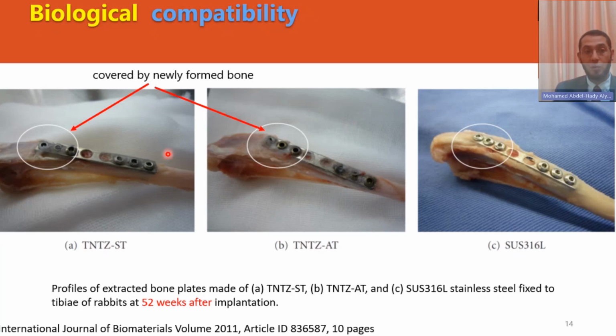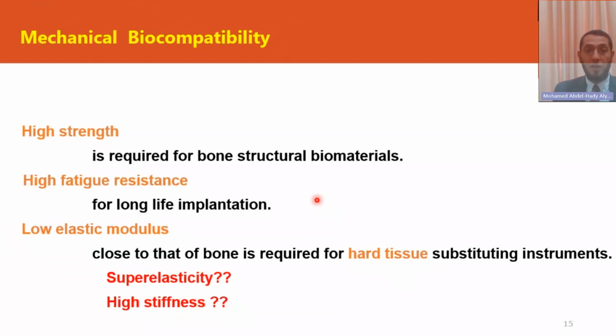Here is an example of the bone plate after implantation. One alloy that's called TNTZ, titanium, niobium, tantalum, zirconium, is good. All elements are very good. Compared to stainless steel, which contains nickel and chrome, you can see here the new bones are growing. The new bone is growing, but with stainless steel, it is not growing. So this means that the environment is very healthy around the TNTZ alloys, compared to the alloy that contains nickel and chrome. So again, the growth of the new bone is a function of the alloy and the alloy composition.